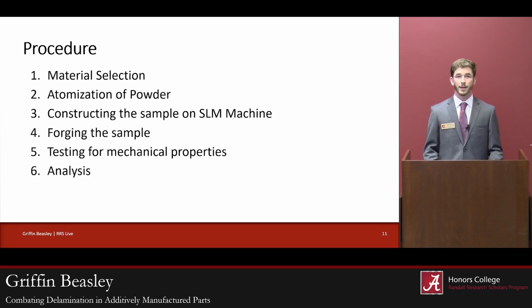After we have obtained our metal powder and also a three-dimensional model, most likely of some stock piece such as a bar or a rod of preset dimensions, we will load them both into a selective laser melting machine and create our first test part. We will put this part through the forging process, and then we will extract test samples to be used in the testing for mechanical properties and some microscopy analysis. After we have obtained hard data values for our mechanical properties, we will compare these properties to properties of similar kinds of steel to try to determine exactly what effect the forge welding had on the additively manufactured part.